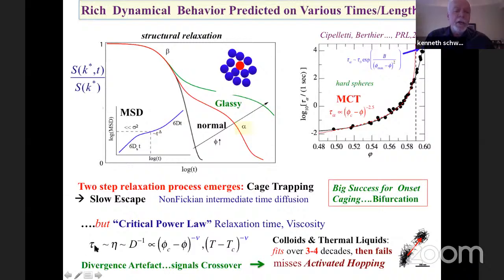And it predicts that the relaxation time, the viscosity, the inverse diffusion constant, they all follow such a critical power law with an exponent that is predicted from knowledge of the structure. So here's some work from the Montpellier group, both experiment and simulation, which shows over about 6 orders of magnitude, which is pretty much the state of the art, the log of the alpha relaxation time versus volume fraction. The points are the simulation and experiment, and the curve is the mode coupling prediction of a critical power law. And you see that it can be fit.